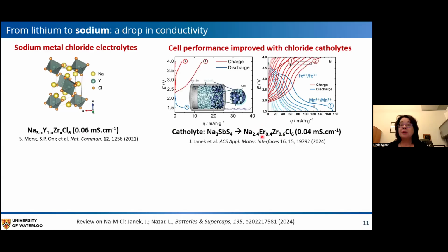This shows the equivalent of an erbium zirconium with similar conductivity. And this is just a paper from Jürgen's group where they swap out a sodium antimony sulfide, which is a very, very highly conductive material, with this halide. And they actually see improved cell performance despite the much lower conductivity of the halide.